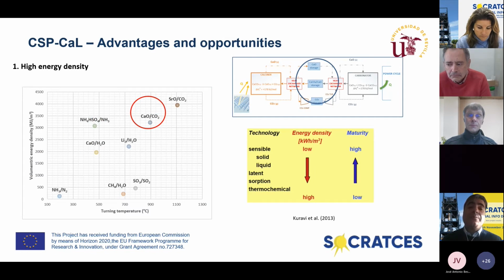Which are the advantages and opportunities? If you have seen some of the previously published papers related to the project or previous presentations, we repeat it, so I will go relatively fast through them. Well, it has a high energy density. Here you have represented the turning temperature and the volumetric energy density for different pairs. But you can see how the calcium carbonate decomposition, calcium oxide and CO2, has a high volumetric energy density, and a turning temperature around 900 Celsius degrees.